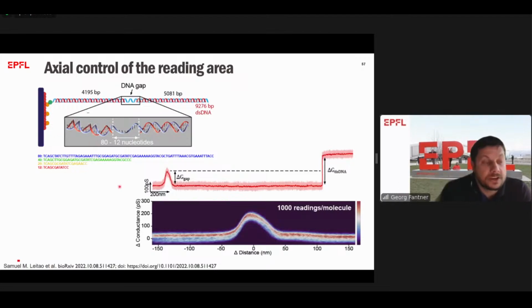So now the peaks actually go in the other direction, because when you get to a gap region, you have less obstruction, so the current goes up, but it's very well visible. And here is an example of really measuring this gap size here very many times. There's 1,000 readings on the same molecule, and we can average and we can get really very high resolution with that,